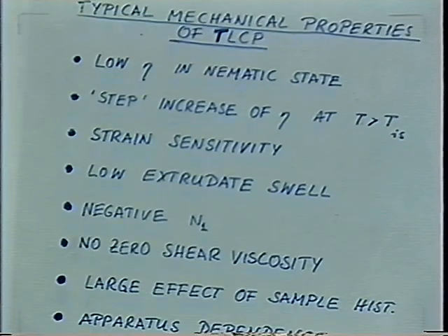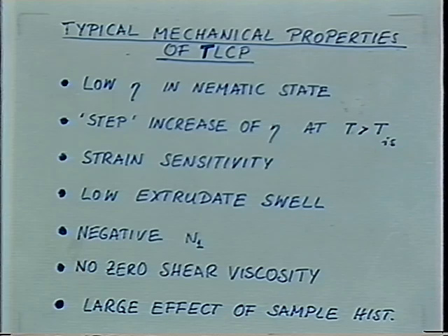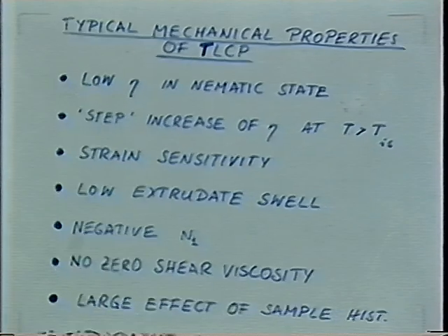And then when you have a shear apparatus or rheological apparatus which uses very thin samples, you will have those surface effects dominating as compared to the bulk effects. And then the different apparatus will give you very different results. So rheology will be very interesting of those systems.